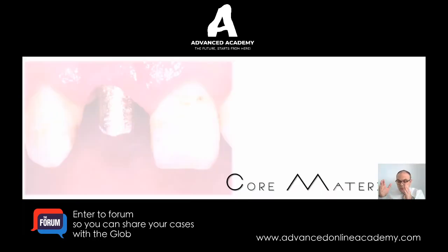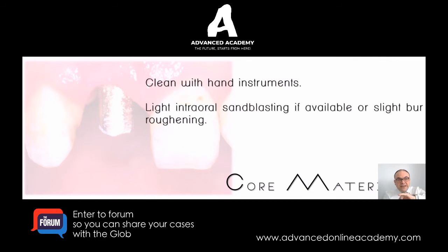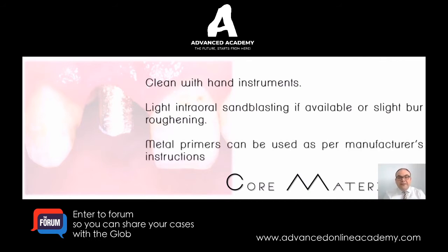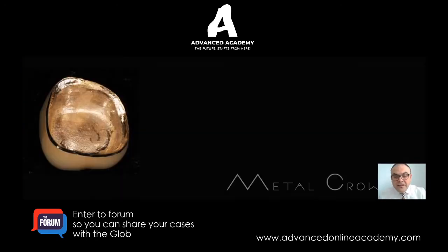So now we've prepared our enamel, we've prepared our dentin. Now our tooth is ready. If we have core materials, let's say I've made a cast post and core, or I have composite, or a metal amalgam, you can clean it with a hand instrument, a slight roughening with a diamond bur. Light intraoral sandblasting is also recommended. If you have a metal core, you can use a metal primer on it. That will enhance the chemical bond to that metal material.